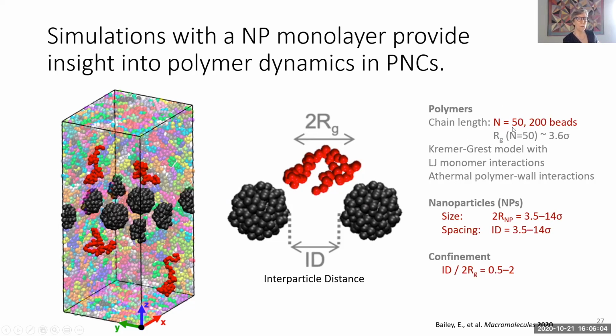So most of the results will be at 50. And we can vary independently and in a controlled way, right? We can independently control the particle size and how far apart they are. And so we can combine those together, and then we can also define the confinement parameter, which is the interparticle distance now relative to the RG. All right, so relative to a real nanocomposite, when you have particles hither and yon, this is a much more defined system, and we can look at the impact of particle size and their separation on diffusion.